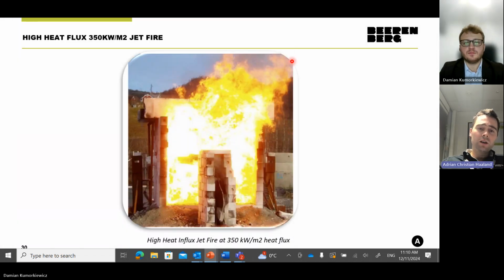Here's what we call high heat flux jet fire testing. The primary difference from a standard jet fire is actually that the chamber is larger, so you generate a much larger flame inside a recirculation chamber, which makes the flame less transparent to heat radiation and as a consequence increases the heat load inside the fireball. There are some other differences as well, but that's primarily what you do.